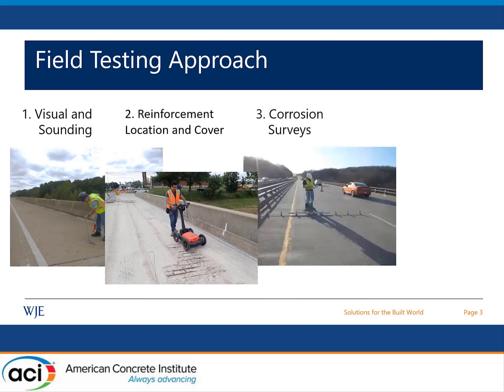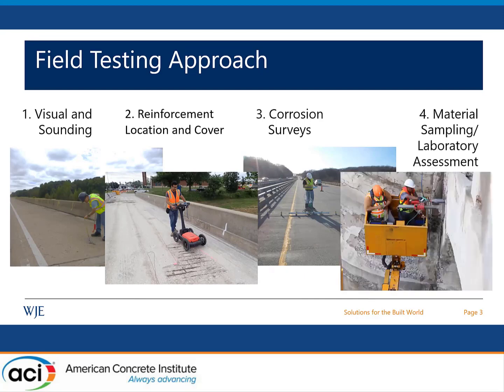And we do corrosion non-destructive evaluation to provide an indication of the corrosion risk and also identify location of active corrosion. And we use half-cell potential, corrosion rate measurements, and concrete resistivity for that. And then we also collect material samples and perform laboratory testing.